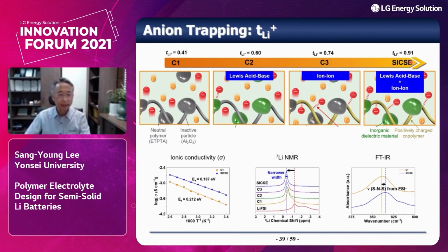In addition, we have measured ionic conductivity, no problem, and the single ion conducting polymer electrolyte can provide higher ionic conductivity than the control sample. We have also measured NMR chemical shifts, and from the FTIR measurement, we have demonstrated that the FSI anions were captured by the cationic polymers.